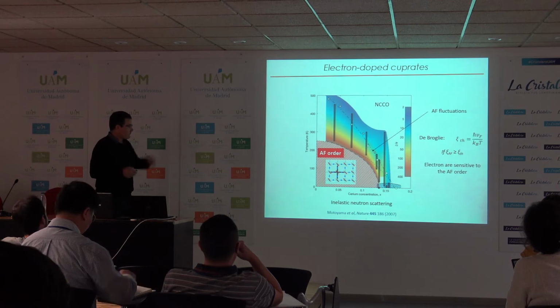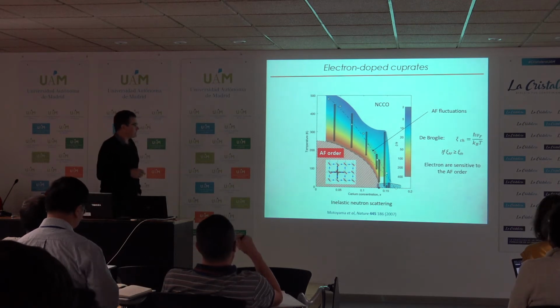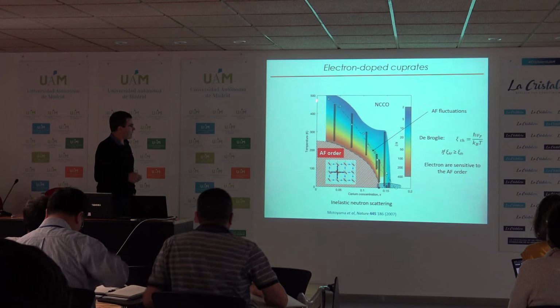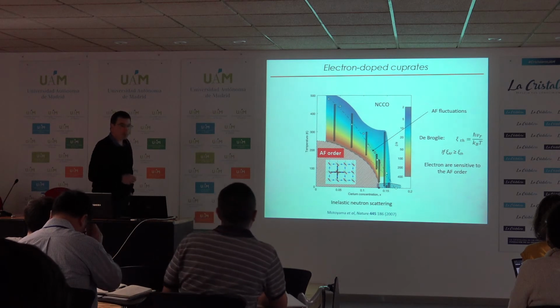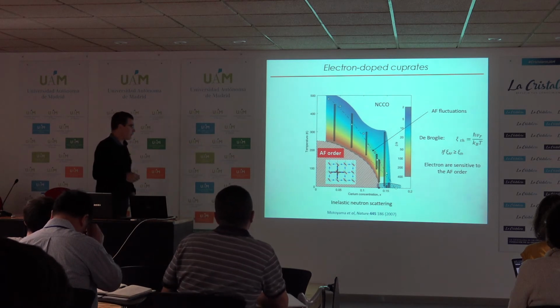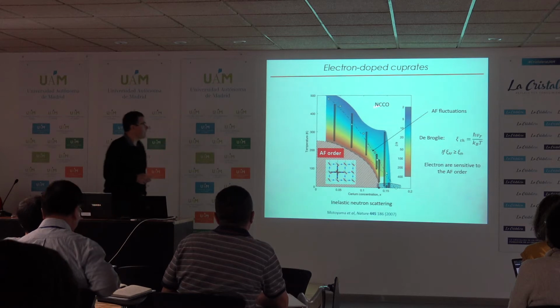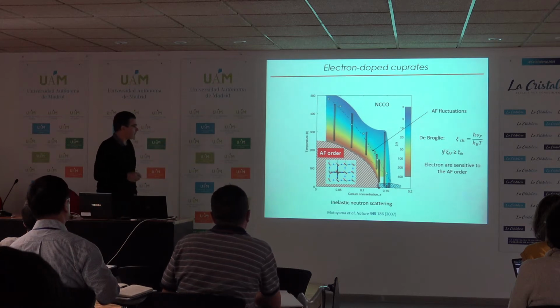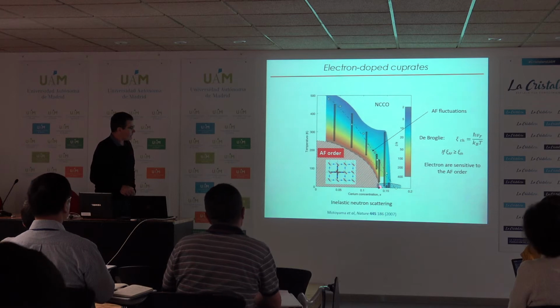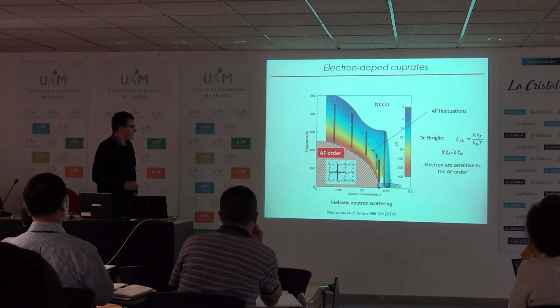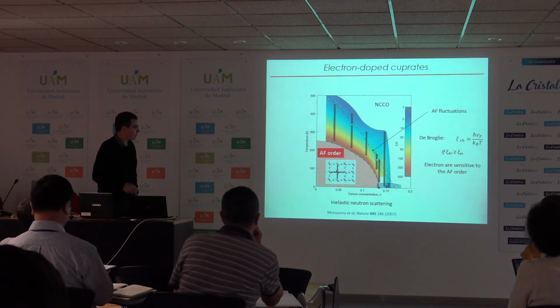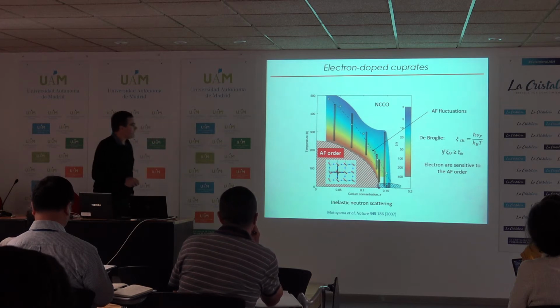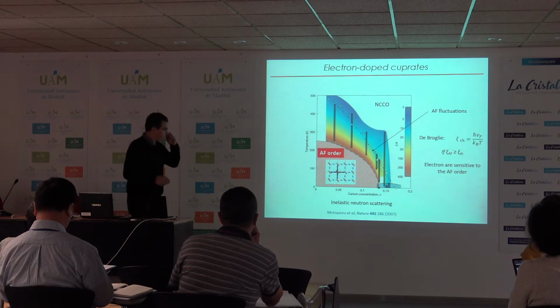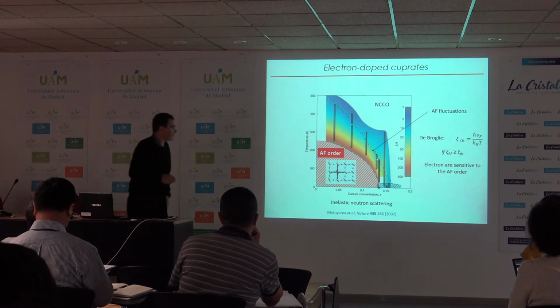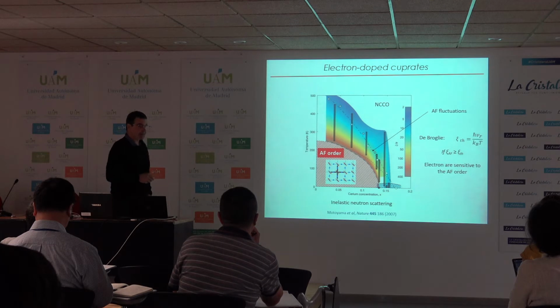I'm showing here a phase diagram, temperature versus doping, for electron doped cuprate obtained from neutron measurements by the group of Martin Greven on the NCCO compound. In red here, what you see is the antiferromagnetic Mott insulating state that extends up to 13%. And here in the color map, what you see is basically the correlation length of the antiferromagnetic fluctuations.